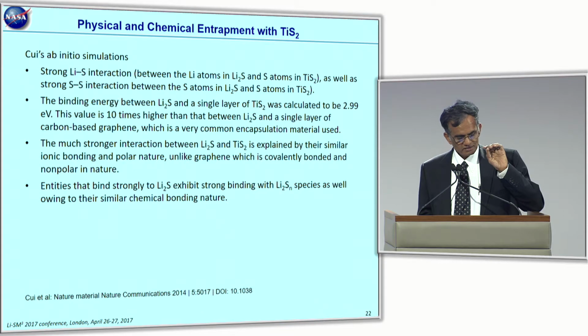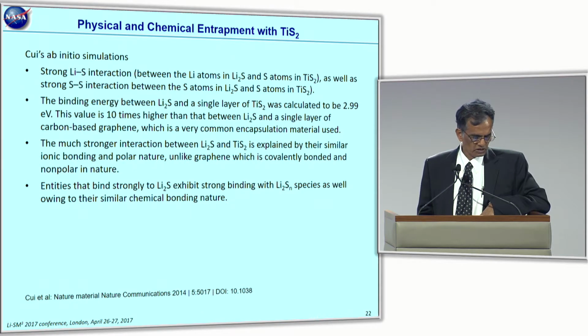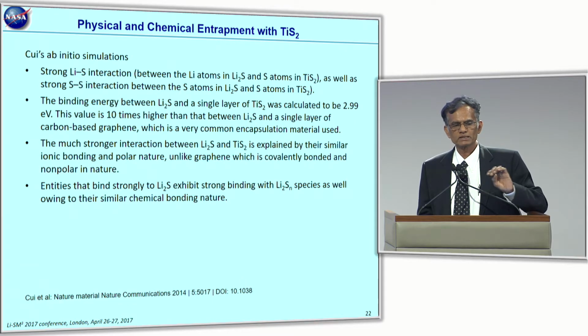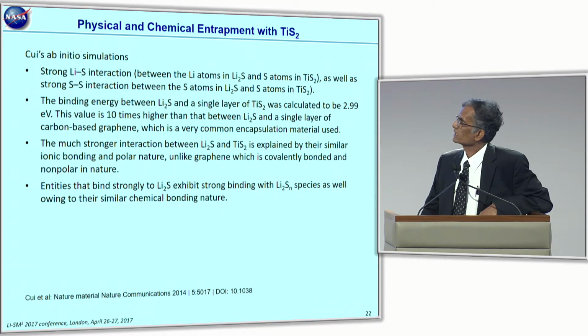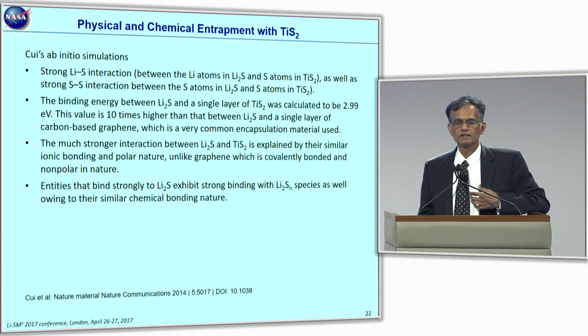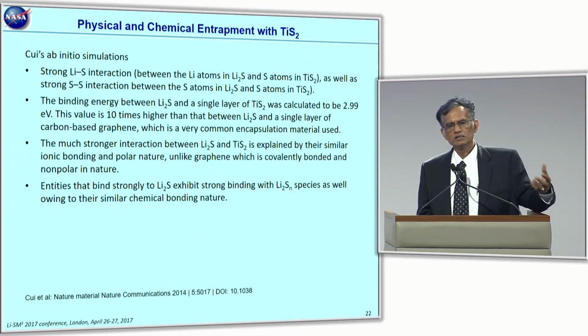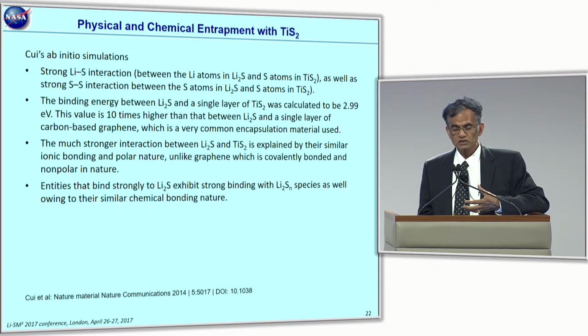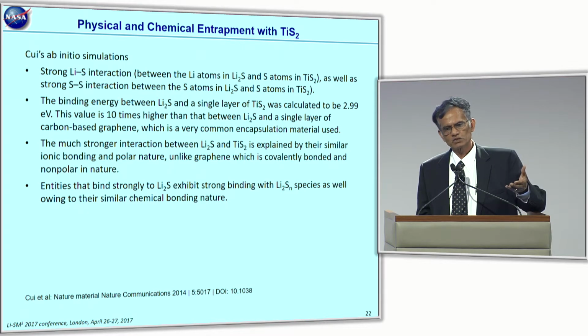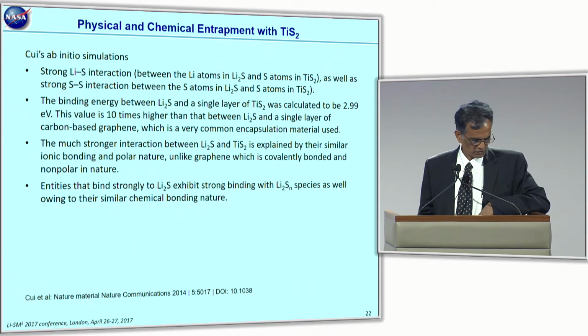And taking a clue from Cui's work, there's actually some understanding provided by his recent papers, where he's talking about, based on the calculations that were done, enhanced bonding between sulfur in the cathode and titanium in the TiS2 being polar. That binding energy seemingly is 10 times higher than what you would see with the carbon-based materials, even graphene oxide. So it's no wonder that once we have these materials in the cathode, we have less of this shuttle effect coming from such cathodes.